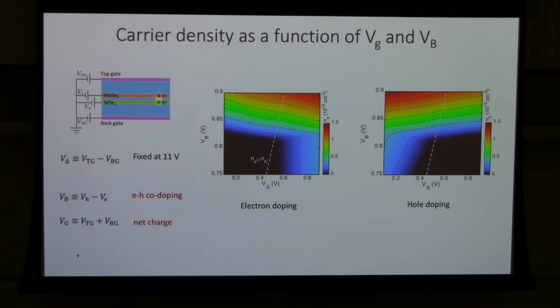So we will have the MoSe2 and WSe2 layers separated by about 3 nanometers. We will fix the vertical electric field to be a relatively large value by setting the top and bottom gate voltage difference to be 11 volts. That just helps to reduce the effective band gap between the conduction and valence band. On top of that, we will apply a bias voltage.